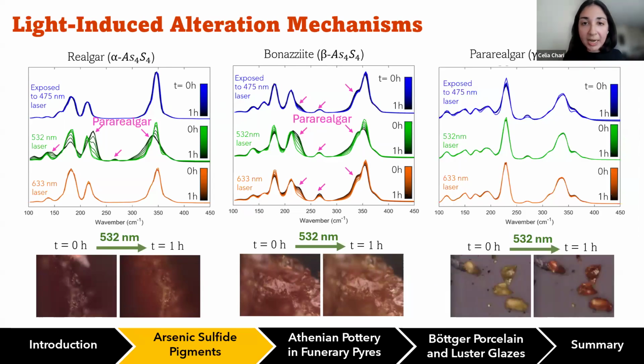As a sanity check, I did also look at para-realgar using the setup to confirm that we're not seeing any additional secondary reactions. And structurally, para-realgar remains as para-realgar during all of these exposures to different wavelengths. But visually, one thing that was really interesting was that the color of para-realgar does change when it's exposed to green light. The thing is that this color is not permanent. When you remove that laser source, the color will eventually go back to being yellow.